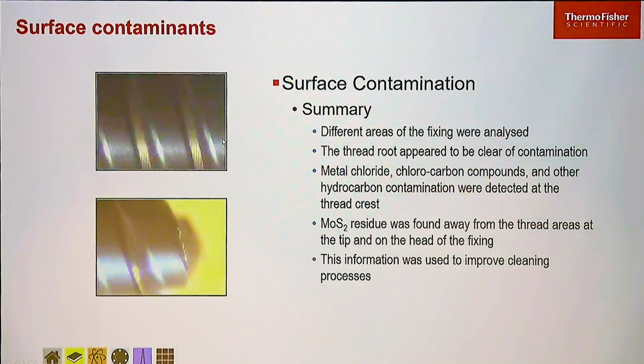And so we're able to analyze different areas quite easily. One thing I would say, it was quite deliberate that we mounted the sample in this direction so that the threads were running this way. The X-rays on the Nexsa and K-alpha instruments, so the Nexsa is the one that's here at NIAR, the X-ray source comes in from this direction, and so that means we could access all the areas on the sample. So you do have to consider the geometry of the instrument.